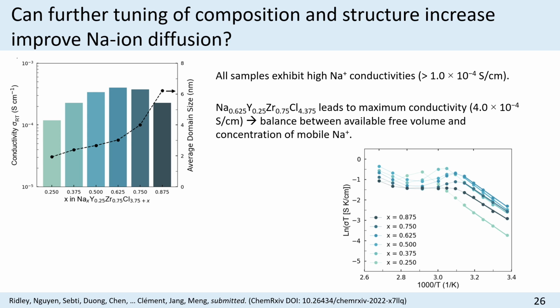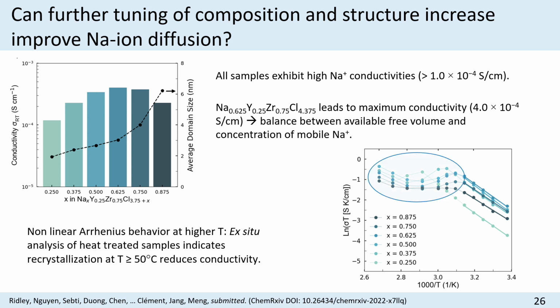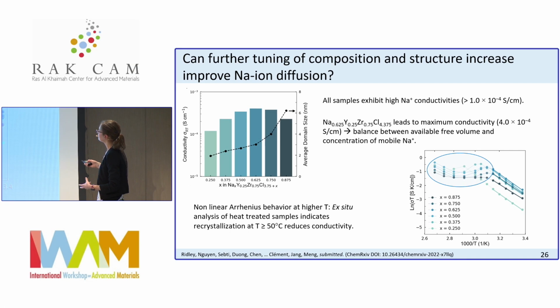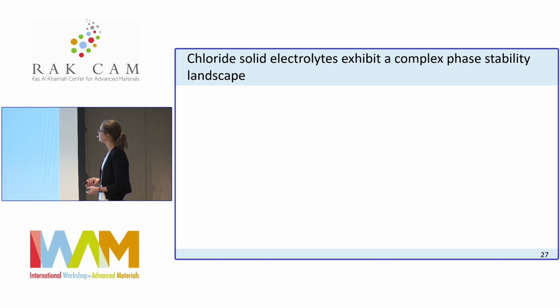And this is true for the low temperature corner of this plot. However, if you go to higher temperature, you now start seeing a nonlinear behavior. And so what's going on here is that you're recrystallizing the material. So we had formed these amorphous materials that conduct well at low temperature. But if you start to heat treat those materials or increase the temperature in your electrochemical impedance spectroscopy measurement, now you're starting to recrystallize the material. So they're not very stable. And that recrystallization leads to a loss of performance, a loss of ionic conductivity.